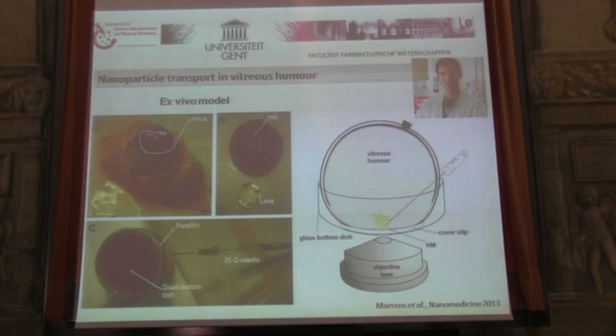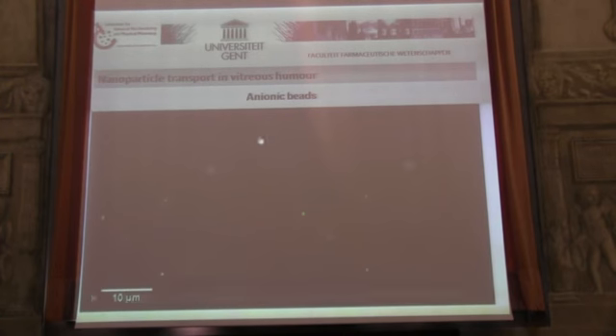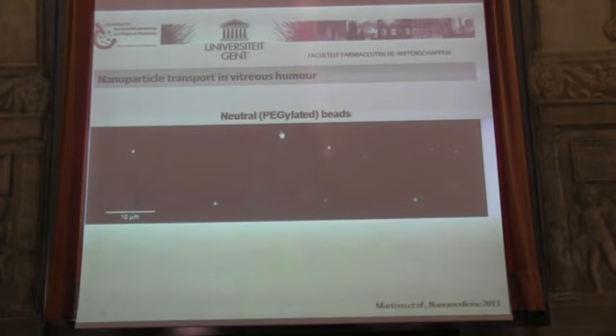So then we put this eye without the lens upside down in a petri dish with a glass bottom indeed, so that we can do microscopy. And then we inject the particles near the observation volume. And then we get these particle images. So positively charged beads. So this is the raw movie and this is the processed movie with the trajectories. These are anionic beads. Yeah, looks not that much different, a little bit more mobile perhaps. And then pegylation, no surprise, massive mobility.